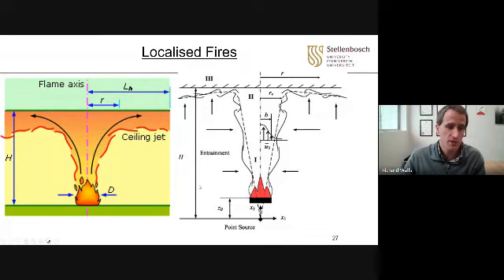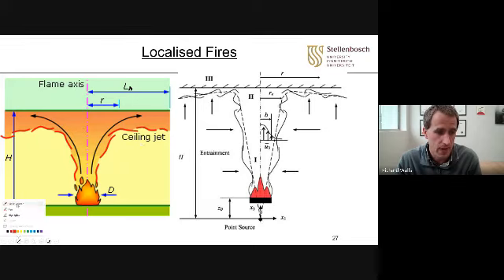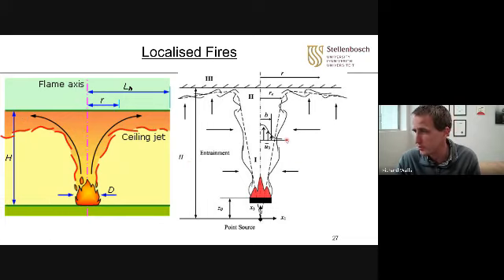You can also have localized fires. So for instance, if you have a transformer or something. So a transformer fire, a pool fire, a petrochemical fire, a tank fire. You can have a localized fire where it's got a distinct diameter, a heat release rate that you can calculate, 500 kilowatts a square meter or 1,000 kilowatts a square meter, depending on your fuel. And then the hot gases rise and then disperse, and you may get ceiling jets. And this you can also use to predict the behavior and temperature that you would use, and then you can design your structural system, your walls, your slabs, whatever it is for this.